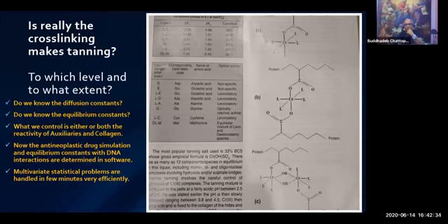Look at the right-hand side of the picture. You can see structures, chemical reactions at the structures A, B, and C. A represents a single point attachment of mononuclear chromium with a carboxylate side chain of glutamic acid or aspartic acid in a single polypeptide chain. B represents the same mononuclear chromium, but cross-linked between two polypeptide chains of collagen.